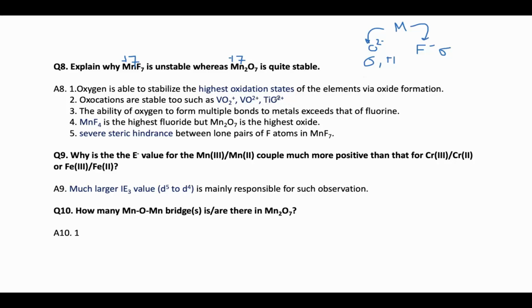Now the ability of oxygen to form multiple bonds, that is a sigma bond and a pi bond with the metal center, exceeds that of the fluorine that I have discussed just now. Since oxygen has this O2- negative charge, it can actually form sigma and pi bonds with the metal centers, which is not possible in case of fluorides. That's why manganese can go only up to Mn+4 in fluorides. So MnF4 is the highest Mn fluoride, but Mn2O7, that is Mn+7, is the highest oxidation state oxide of manganese. But the actual reason is another one.